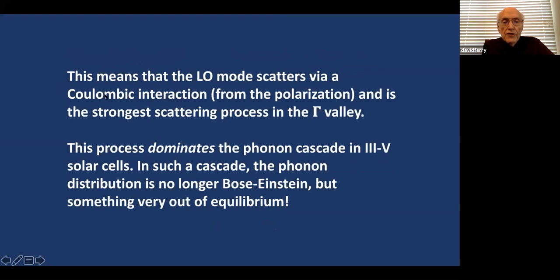Okay, so the LO mode scatters via Coulombic interaction from the polarization. And in the gamma valley where the electrons are created by the photons in the solar cell, it's the largest scattering process there, except for the scattering from gamma to the satellite valleys, which is bigger because of the large masses and density of states in the satellite valleys. But for that phonon cascade, this LO mode dominates the phonon cascade in 3-5s. Now, that means that it's so efficient in emitting phonons, these phonons will be driven out of equilibrium. So they'll get away from their normal equilibrium distribution and they're no longer Bose-Einstein in shape, but something much different when they're out of equilibrium.